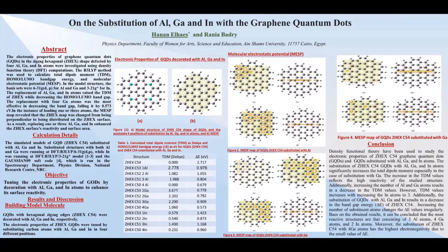Based on the obtained results, it can be concluded that the most reactive structures are those consisting of 3 aluminum atoms, 4 gallium atoms, and 2 indium atoms. Moreover, the substitution of ZHEX C54 with 4 gallium atoms has the highest electronegativity due to the small value of the optical band.